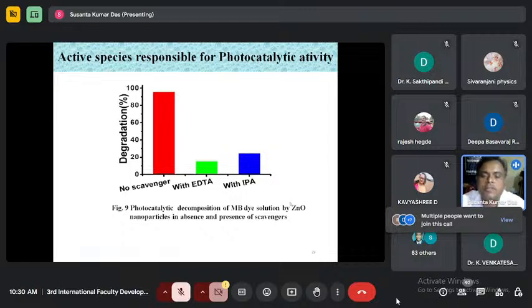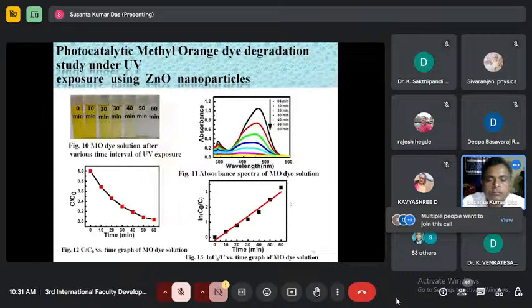There are two types of scavenger we had to use. He had suggested that one is EDTA and another is IPA. So we found that with the addition of scavenger, the reaction was reducing. This confirmed that all the things that were coming were because of the photocatalysis activity only, not because of the adsorption process. So then we continued with other materials like methyl orange.